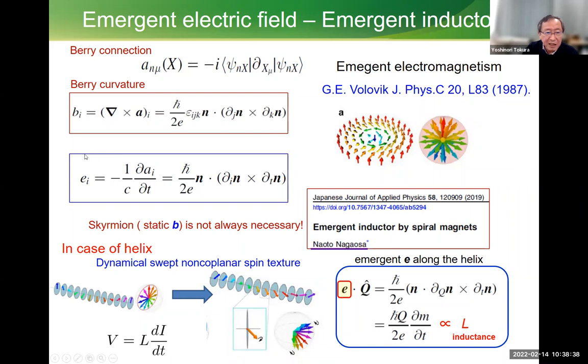Okay. And so we can have a kind of Faraday's law. The electric field is the time derivative, maybe 1/c is not necessary, of the Berry connection. So in terms of the real-space spin texture, we can describe something like this. The electric field along the x direction is the x-direction derivative of the spin moment polarization vector, but also includes the time derivative of the polarization, the m dot. So this means if the non-coplanar magnetic structure is dynamically swept, it can also generate electric fields.